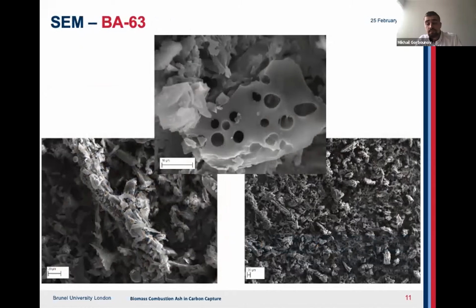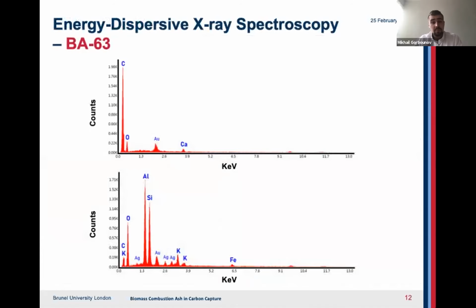Here are the SEM images; they do depict the nature of our BA63. As can be inferred, the ash is mainly carbonaceous, with rare inclusions of glassy silicate spheres. The presence of carbonaceous species is clearly shown in the top picture. Furthermore, these assumptions were further confirmed by a carried out EDS analysis. And the energy dispersive spectrometry did corroborate the theory that carbon is the prevailing element, as data similar to the one presented in the top figure has been acquired throughout the sample, making the image shown representative of the bulk of the material. However, there were also constituents that have been found within the obtained BA63.